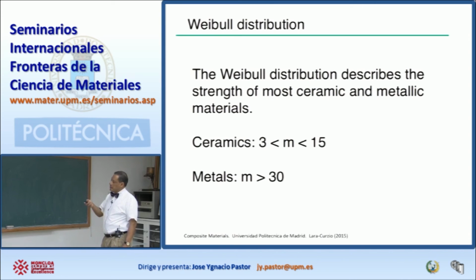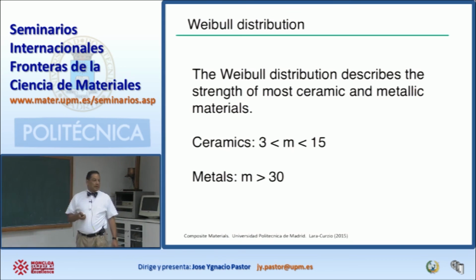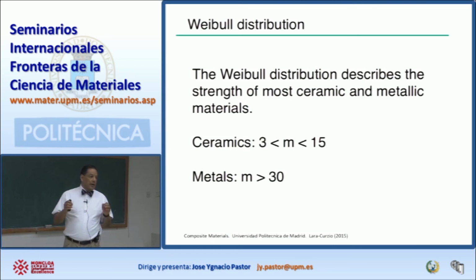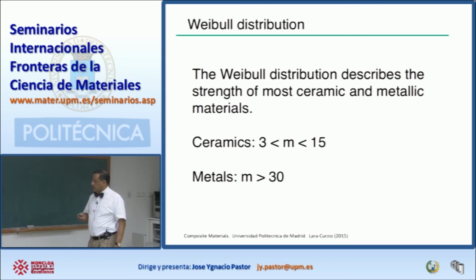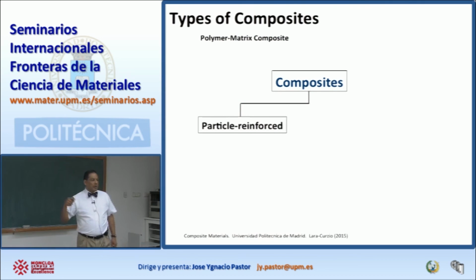natural phenomena. And in the case of ceramics, we find that for most ceramics, if you look at the tensile strength, the Weibull modulus varies between 3 and 15. Okay, materials like silicon nitride, silicon carbide, you know, they are around 10. And then if you have metals, the Weibull modulus is actually very high. And that means that you are going to have less variability whenever you test metals than when you test ceramics. And this is why we build bridges with metals and not with ceramics. You know, the variability that you have with metals is much less than what you have with ceramics. Okay, any questions? So this is the Weibull distribution. This is one of the most important contributions when it comes to reliability theory of ceramics and many materials in general. And we're going to return to the Weibull distribution here in a minute.